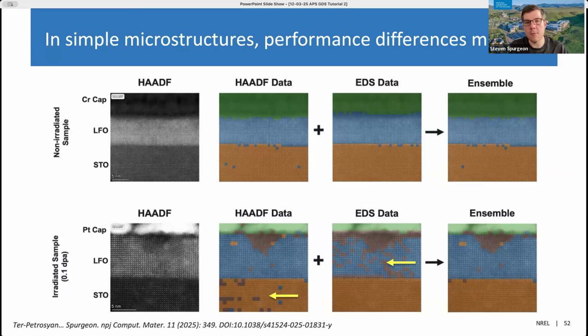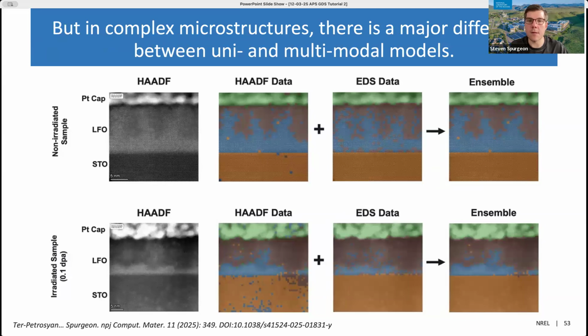And that's because radiation damages not just the crystalline lattice, but it actually can cause migration of different alloying elements, can cause chemical state changes in the material. And that is stuff that is more challenging to capture in the imaging than in the spectroscopic data. When we get to really complex, highly irradiated microstructures, these models perform even better. And in particular, we find that ensemble approaches are really essential to look at highly irradiated, highly disordered materials, where again, disorder manifests not just in a change in the lattice, but also the composition of the material.